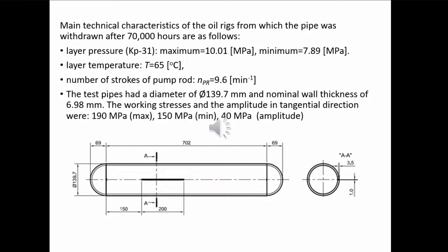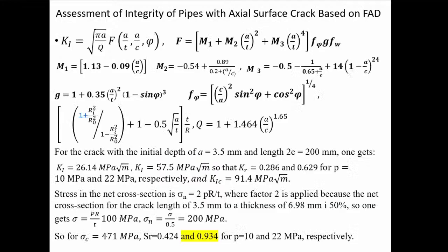You can see in this sketch that artificial crack was made in this prototype with length of 200 millimeters and depth approximately half of the thickness, that is 3.5 millimeters. Now to evaluate the stress,